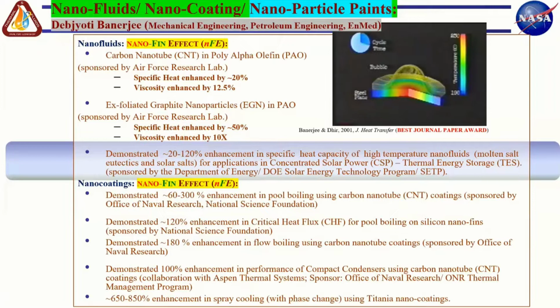So we decided to do this experiment using silicon nanofins that were etched on a silicon wafer, and we repeated the same experiment. And silicon has a lower thermal conductivity and diffusivity than carbon. But to our horror, silicon actually gave us higher critical heat flux. And we consistently demonstrated this for flow boiling as well as for making nanocoatings on condensers as well as for